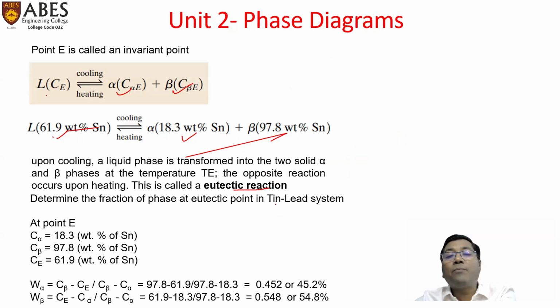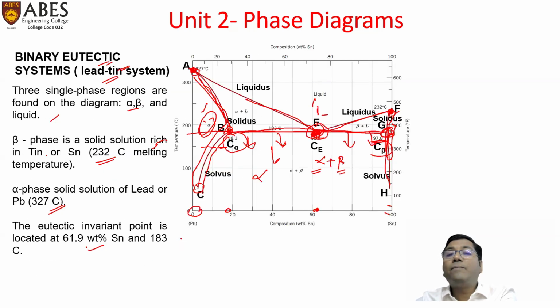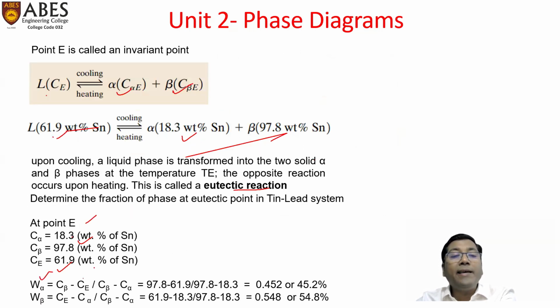To determine the fraction of phase at the eutectic point in the tin-lead system, at point E, C alpha, the weight percent of tin, is 18.3. The composition of alpha would be 18.3, beta would be 97.8, and Ce would be 61.9. So we can calculate the mass fraction of alpha. Since alpha is this point, the mass fraction of alpha would be the opposite arm, GE, divided by the total BG. That means C beta minus Ce upon C beta minus C alpha. When we calculate this, we will have 45.2% mass fraction of alpha phase.